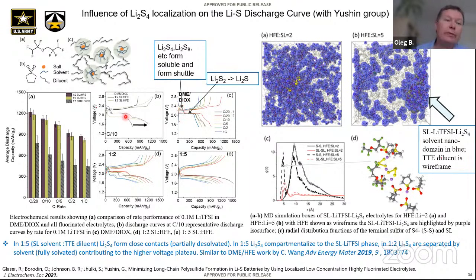And it turns out if we take a diluent approach of what PNNL calls highly concentrated localized electrolytes, meaning there is a solvating species of sulfolane with a lithium TFSI salt, and we put in a diluent, and following their work it is just TTE, a highly fluorinated ether diluent, then the lithium salt will segregate to the sulfolane domains, right? Now locally it's going to be a very, very high concentration regime. And how does it change?